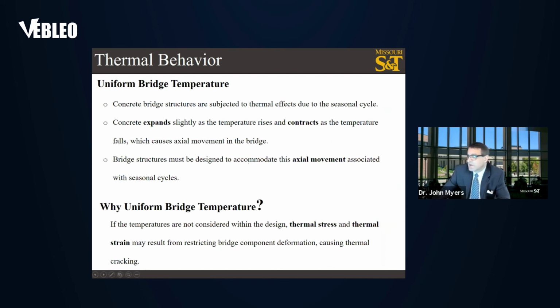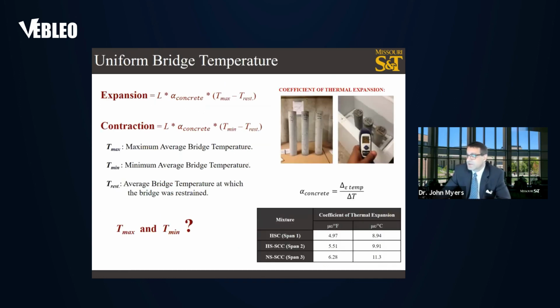Uniform bridge temperatures are critical because of seasonal changes, expansion, and contraction due to thermal changes, and this can affect the bridge behavior. If this is not considered in design, especially in continuous constructions, it can result in cracking and deterioration of the bridges and structures. In order to evaluate the behavior of the concrete, we had to understand what the thermal expansion and the coefficient of expansion and contraction is. In order to do that, we could make specimens and put them in a freezer, put them in an oven to then develop the coefficient of thermal expansion of each of these materials that was used in the actual bridge construction.